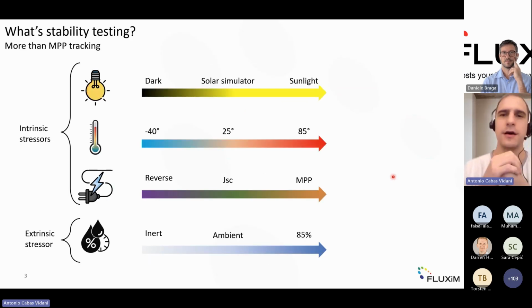So let's take first a step backward in order to move forward. What is effectively stability? Stability is the combination of multiple stressors. This entails intrinsic stressors and extrinsic stressors. The latter one is essentially how your device behaves when it's subjected to the environment, so oxygen and humidity essentially. And you see that each stressor has a wide range of intensities. We can go with light, going from dark up to sunlight, so this would be outdoor conditions. The bias goes from reverse to MPP and all the steps in between. And then the extrinsic, so the humidity can go from inert, so no humidity, up to 85% if you want to create an especially stressing environment.